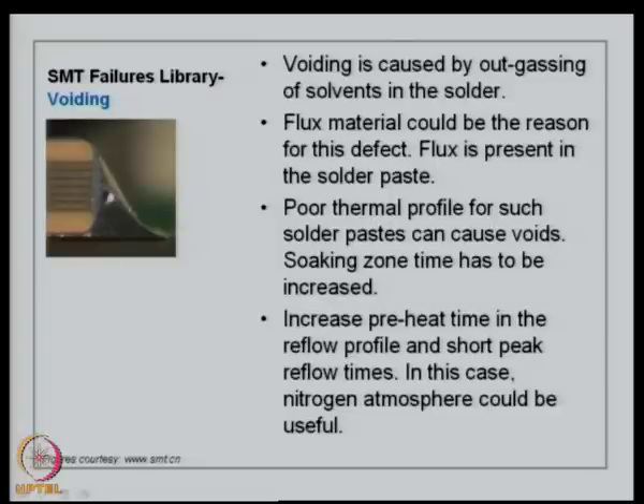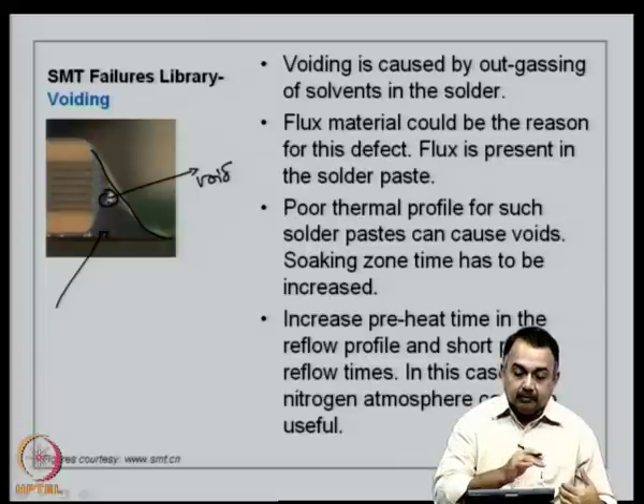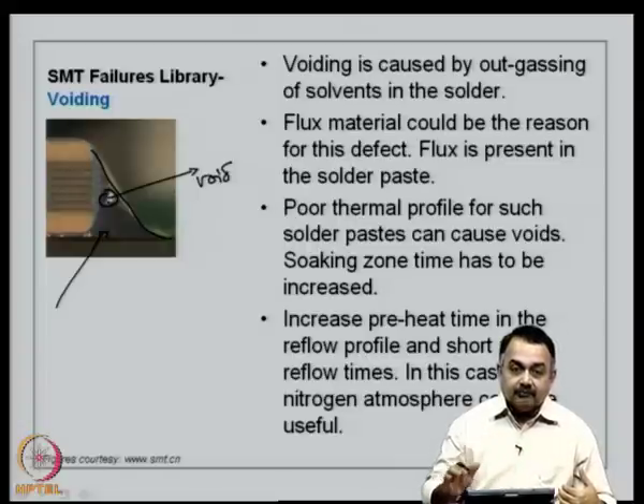The other defect is voiding. Voiding, you can see here, this is a void in an otherwise very good solder joint. Voiding is caused by outgassing of solvents in the solder. So, typically you can assume that this is a very good joint formed, but unfortunately there is a defect which has been caused by outgassing of the solvent in the solder paste material, and that has created a void. Flux material could be the reason for this defect. Flux is present in the solder paste, as you know, and poor thermal profiling for such solder paste can cause voids. Here again you should not approach the reflow temperature fairly fast. It has to be very gradual.